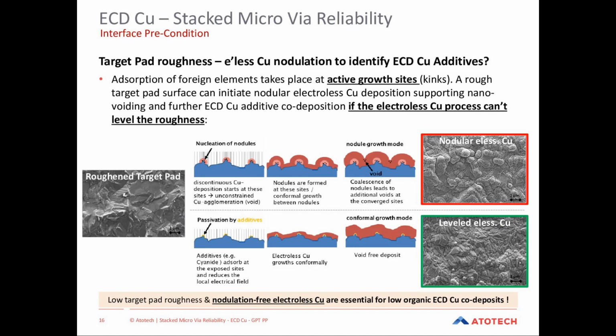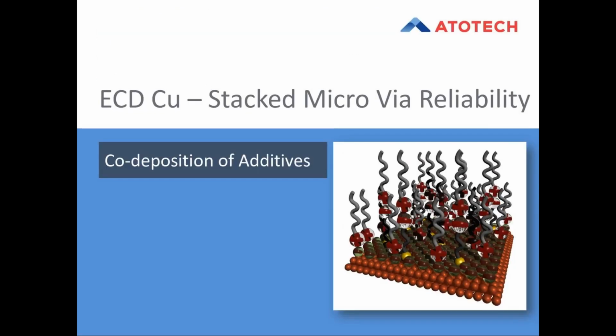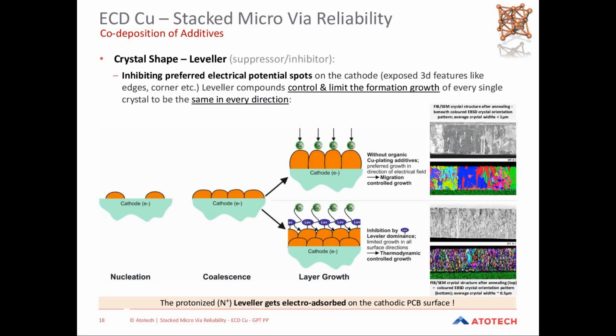But the electroless copper process in this example is also very important to optimize in this regard. We can nowadays use electroless copper deposits which level target pad roughnesses better so that we can prevent nodulation. And if this is ensured as a precondition, it will also be less likely that we have a strong adsorption of electroplating additives. So this was an interesting finding as a prerequisite prior to electrolytic copper plating, to avoid any roughness or nodulation in the processes before electroplating, so that we do not have too many active growth sites later for adsorption of additives.